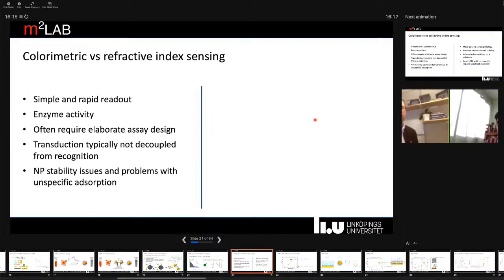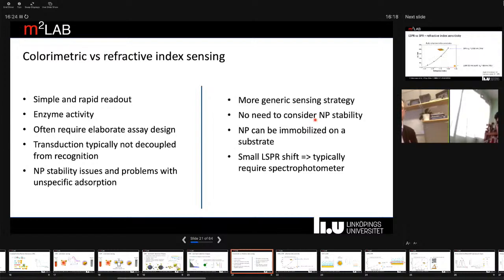And you also have some issues with nanoparticle stability, since colloids are not thermodynamically stable. They tend to aggregate over time, or due to unspecific adsorption of proteins. So that's why we have also paid quite a lot of attention to refractive index sensing. So essentially approaching the same concept as used with SPR, just monitoring small changes in refractive index when biomolecules bind to the surface of nanoparticles. Because this is a more generic sensing strategy, you don't have to consider nanoparticle stability, and you can have the particles immobilized on the substrate. The downside is that the optical shifts here are very small, and you typically require a spectrophotometer of some sort.